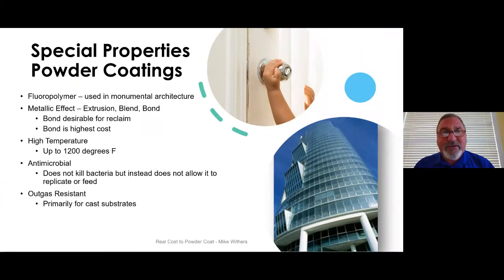Some of the other products that are out there are fluoropolymers, typically used in monumental architecture. However, a customer may tell you, if you're a coater, say, I want the best coating out there. Well, depending on what you're looking at in the end use, a fluoropolymer can be the best coating out there because it gives you the longest performance in the sun. But it is also significantly more expensive than a standard polyester TGIC. So in that case, you may be over-engineering the product. You don't need the fluoropolymer and increasing the cost.